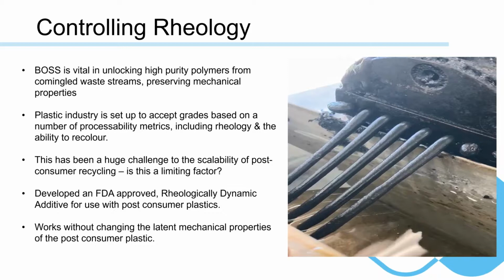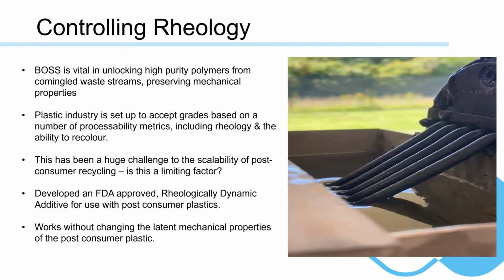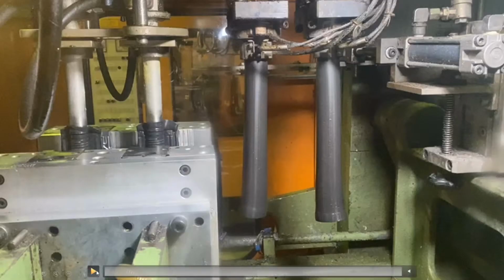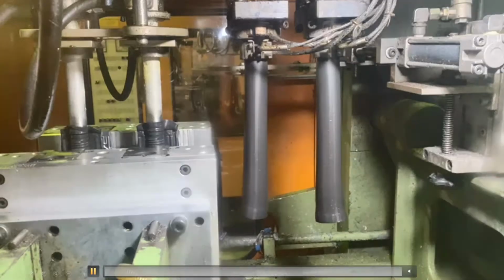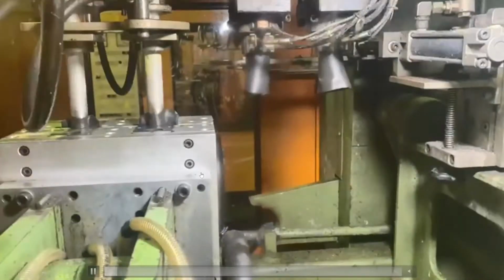So we spent all that time trying to mechanically sort and purify polypropylene and polyethylene. And this allows us to preserve, because there's no thermal history there, the mechanical properties of the plastic. By combining it with the additive, we can then control the melt flow rate, control the rheology, to the point where we're able to make perfect extrusion blow molded bottles.